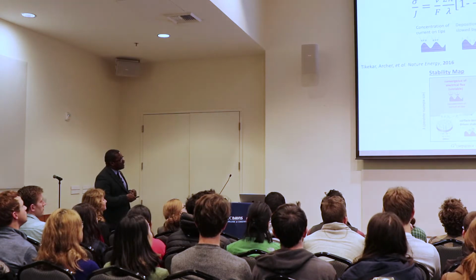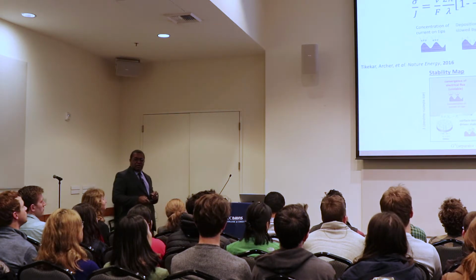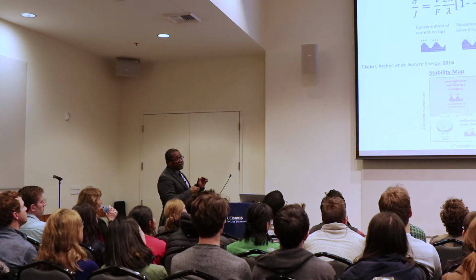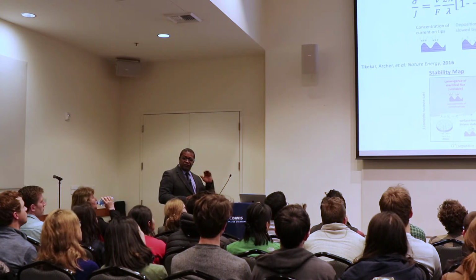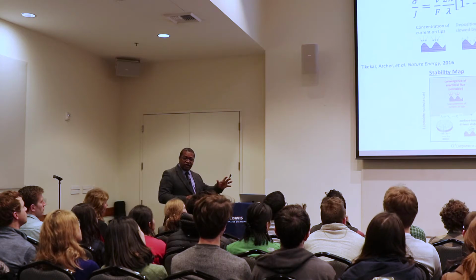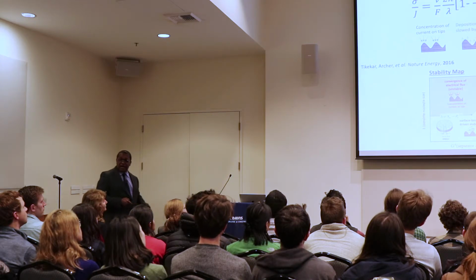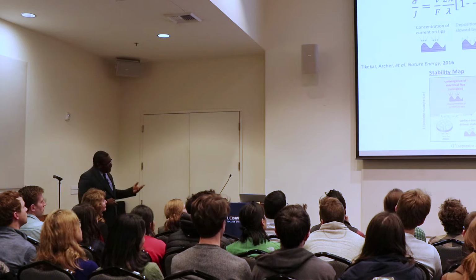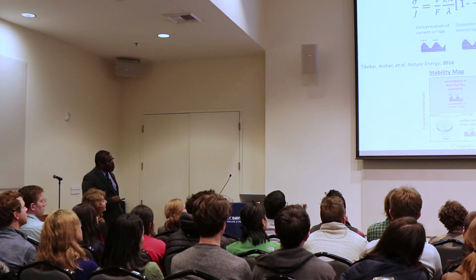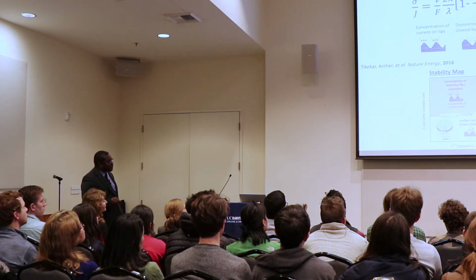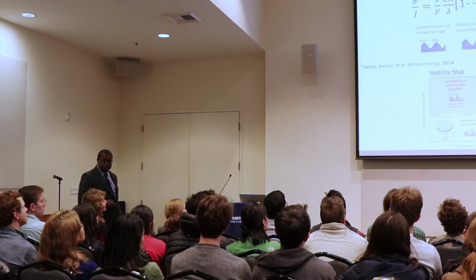Out of this, we can now plot a map. The map tells us where sigma, this growth rate, is positive, which means bad, which means the growth is unstable, where it's negative, and where it's zero. Unsurprisingly, the loci on this map are basically determined by these two groups, P1 and P2.